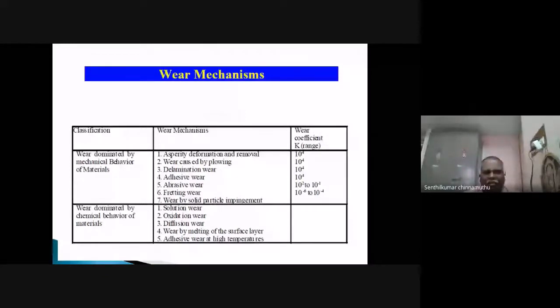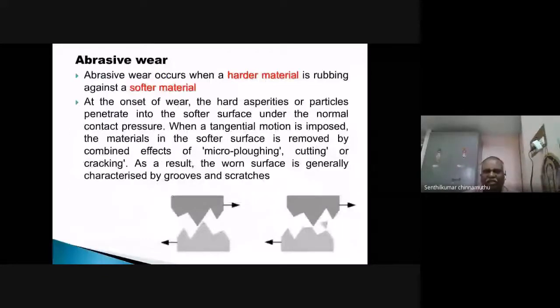Abrasive wear. Abrasive wear occurs when harder material is rubbing against a softer material. The onset of wear, that is, the wear starts. The hard particles are pulled out from the surface due to the applied load or applied pressure. When the tangential force is imposed, the pin material or the softer surface is removed by the combined effect of micro ploughing, micro cutting or micro cracking. As a result, the worn surface is generally characterized by grooves and scratches.